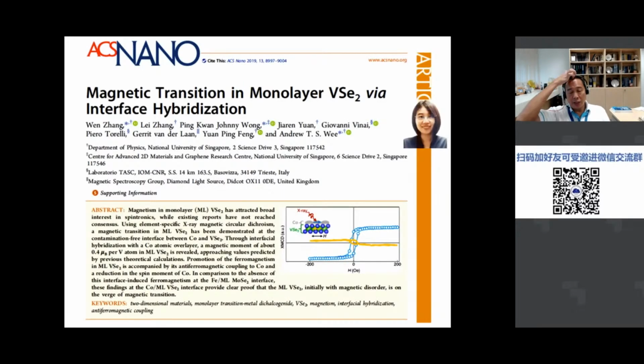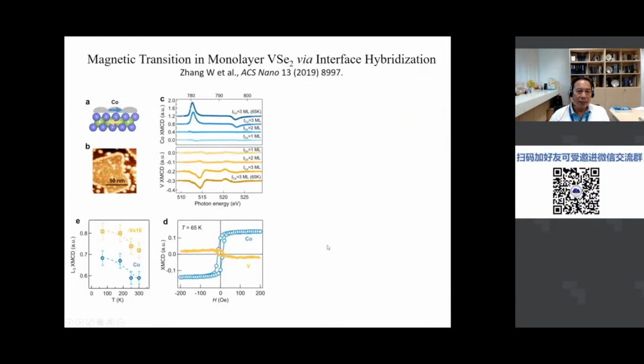And this work is done by Zhang Wen, who also has a professorship in NPU. To summarize, the title says magnetic transition in monolayer VSe2 via interface hybridization. So essentially, as this table of contents diagram shows, you put cobalt on top of VSe2, and it induces magnetism by proximity, and it is anti-ferromagnetically coupled, because you see from the XMCD signal, these hysteresis curves are in opposite directions. And just to elaborate on that, here's STM showing the islands of cobalt or clusters of cobalt on top of vanadium Se2.